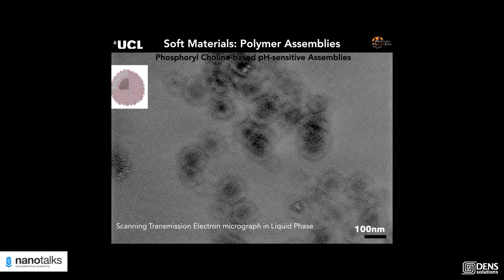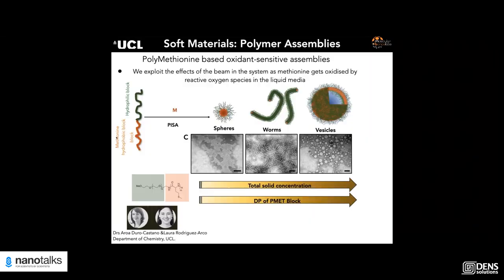In this first example I show a polymersome structure in water imaged by a liquid cell. The structures are fully hydrated — you can see the dense core in the middle and the membrane fully hydrated with no need for staining agents. If you image these systems with dry TEM, the staining can crystallize on the membrane and you have polymer deflation because of the dehydration process of the sample preparation.